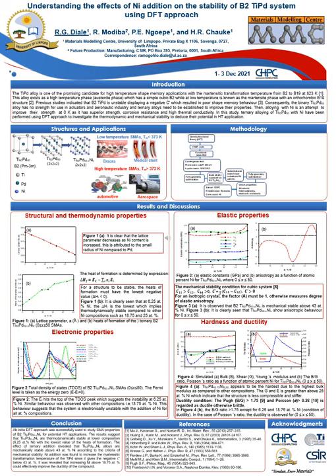At higher temperatures they are applicable in automotive and aerospace industries and actuators. Available actuators are made up of titanium nickel operating at a temperature of 373 Kelvin. There is a need for actuators operating at a temperature above 373 Kelvin, for example in aerospace applications. The calculations are based on the density functional theory as implemented in the VASP code. We used VASP code because of its robustness in determining ground state properties. The exchange correlation was treated with GGA-PBE, which enabled us to obtain parameters close to experimental values.